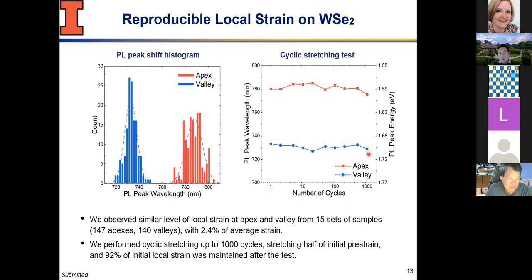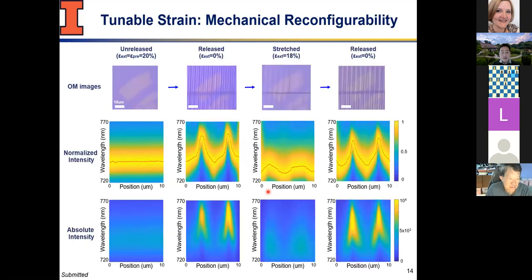And you can do a lot more careful studies at the apex and valley, to see how well they're distributed, and how robust they are with cyclic stretching, because this is on a soft polymer, elastomeric substrate. You can stretch back and forth, and we just want to make sure there's no slippage, and that these strain states will lock stably at the apex and valley. That's what you're seeing there.